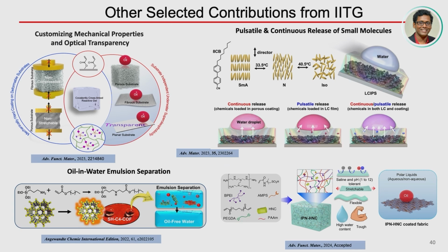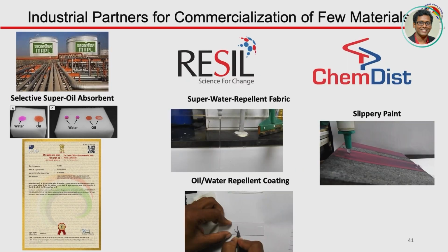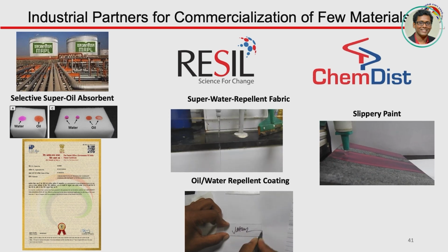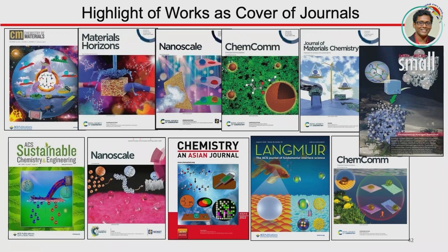Then we have also introduced this kind of water repellent coating in the COF, another porous crystalline material, to associate the selectivity towards the oil phase and repellency towards the water phase, and that's the way you can separate the emulsion efficiently. So these are some of the pieces of work which are going on, and we also have some active collaboration with industrial partners for commercializing some of these inventions from our institute, in our lab, and some of our work has been showcased as a cover page in different journals.